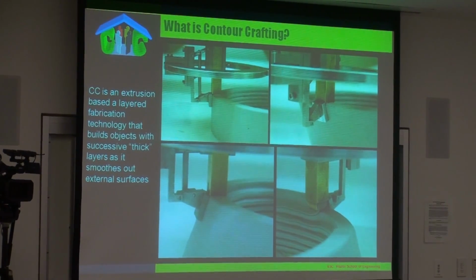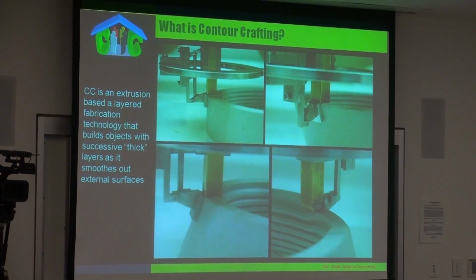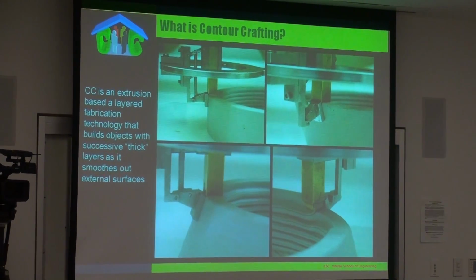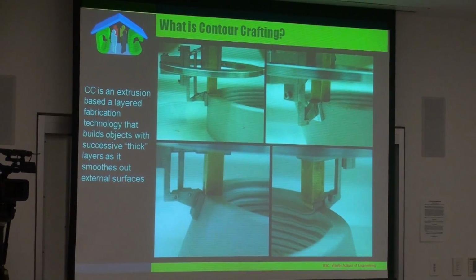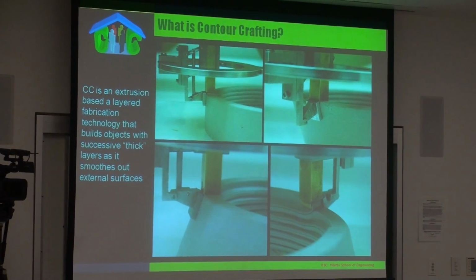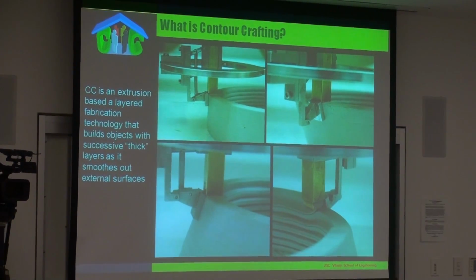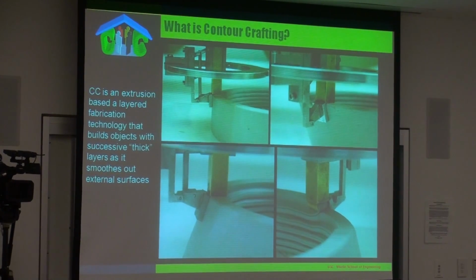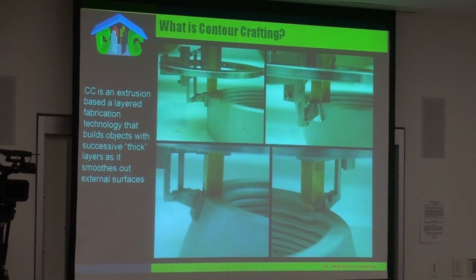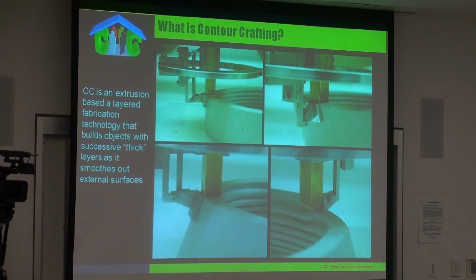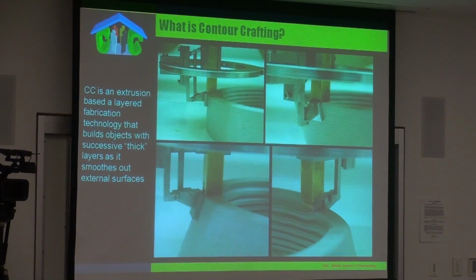So these are some of the early trials, as you see. The layer there is 6 millimeters. Compare that to typical 3D printing that has a layer thickness of under 1 millimeter, usually 0.25 to 0.1 millimeter. And the surface quality here is better than even those that have sub-millimeter layer height. What is the nozzle diameter? In this case it has a square orifice. It's about 8 millimeters. Right.